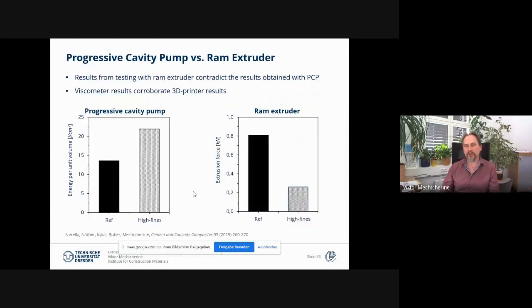So finally, I want to address an issue which, at least in our group, we observed in the experiments, that at least for a particular composition of printable concrete, the behavior with respect to the energy consumption in the experiments with the cavity pump is different if we compare to the ram extrusion experiment. So again, I don't want to go into detail, but what I'm trying to say is, if you test your material with a ram extruder, it doesn't mean you can translate this result directly to the progressive cavity pump.